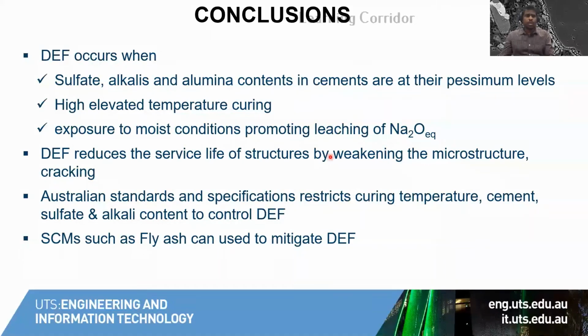So to conclude, deleterious DEF occurs when cement alkalis, sulfate and alumina are at their pessimum levels, and such concrete is steam cured at a very high elevated temperature. And during service of the concrete, there should be access to water, directly or indirectly, to promote leaching of alkalis from the system, so that ettringite will precipitate back in the hardened concrete to cause problems. Once DEF forms in the microstructure, it may weaken the microstructure by producing cracks and cause the concrete to be more permeable.